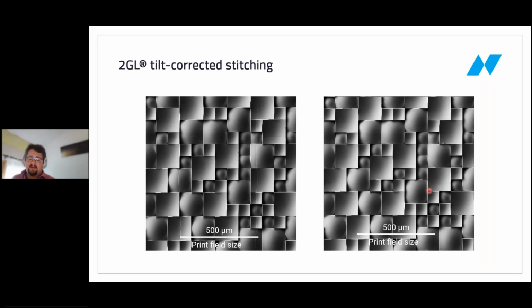This is projecting a homogenized beam, and the quality of the homogenized beam is notably improved because of this tilt corrected stitching approach. And so this approach to 2GL and the tilt correction is used by plenty of our customers for the nano imprint lithography that IPMS also offers you when you want to print one master of a relatively large area and then go into a replication process. So this could be used to improve microneedles, micro lens arrays, anything that you would replicate, or you could correct the tilt mechanically, as we have just seen IPMS is capable of doing now.